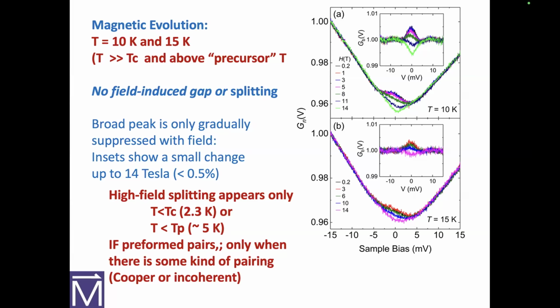So we're significantly more than twice higher than TC. And what we see is very, very little change. Here's the background conductance, and we see a little bit of change, but we absolutely do not see that field splitting or whatever that is. So that only appears below TC, or below 5 degrees, about twice TC.